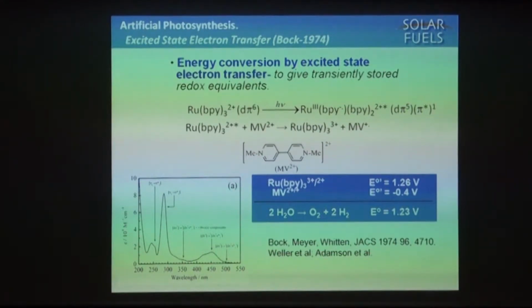That was back then quite a feat. Weller and his group in Germany had shown organic electron transfer and had done some very elegant work. This was a nice straightforward example using flash photolysis of what the products were. We could also estimate what the efficiencies were. But then we could estimate something else, and it really began something new, a new way of thinking. And that is, if you look at this complex, Ru(III), and look at its redox potential, because you could do that by electrochemical experiment very easily, it was 1.26 volts. That means that that complex, after it's oxidized, is capable of doing water oxidation over the whole pH range, from 0 to 14. Methyl viologen, once reduced, MV+, is a sufficiently good reducing agent to reduce protons to hydrogen.